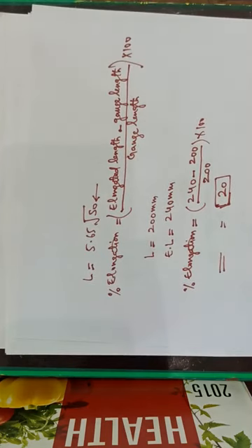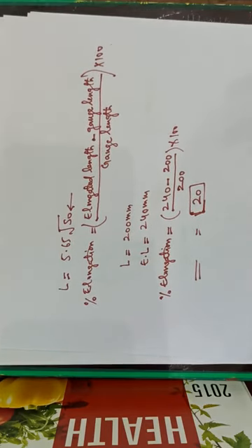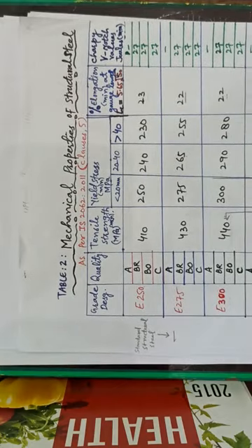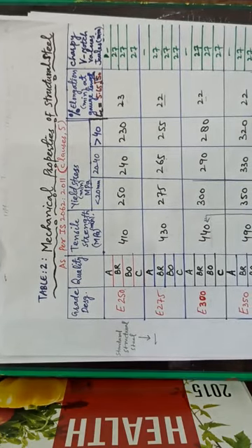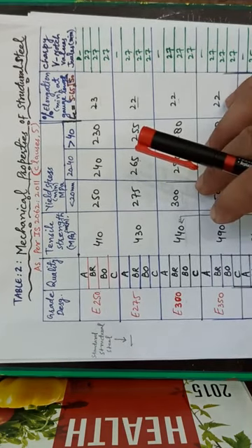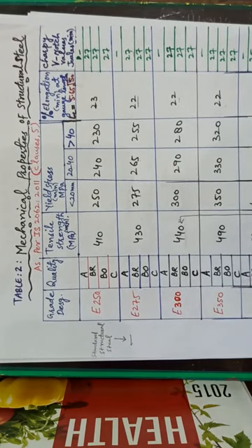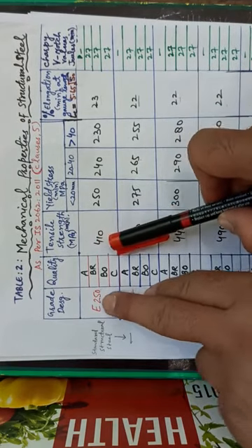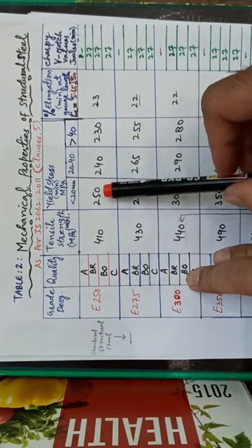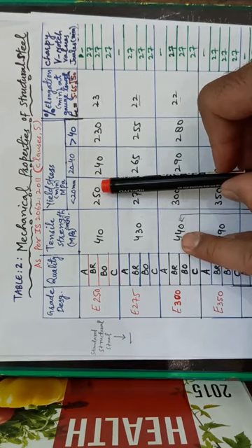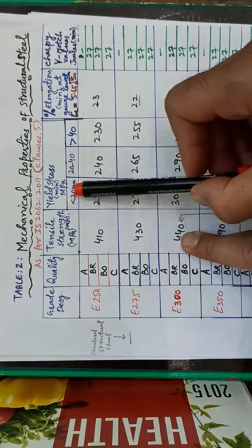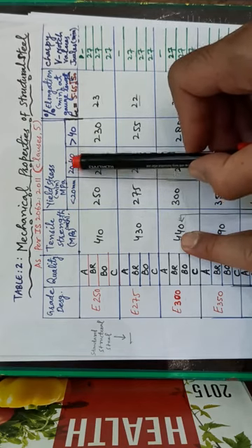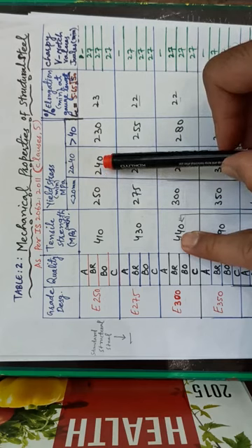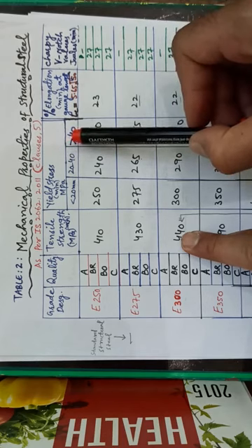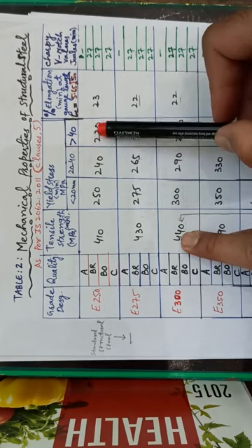The minimum required percentages of elongation for various grades of steel are given in table 2 of IS 2062-2011. As you can see, table 2, mechanical properties of structural steel, clause 5, we have different grades, that is E250, E275, E300 up to E650. The tensile strength for grade E250 is 410, and the yield stress for grade E250 is 250 Newton per millimeter square when the thickness of the member or the specimen is less than 20 mm. When the thickness is between 20 to 40 mm, the yield stress is 240 Newton per millimeter square. When the thickness is more than 40 mm, the yield stress is taken as 230 Newton per millimeter square.